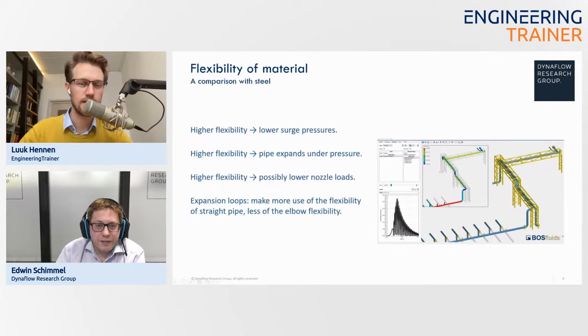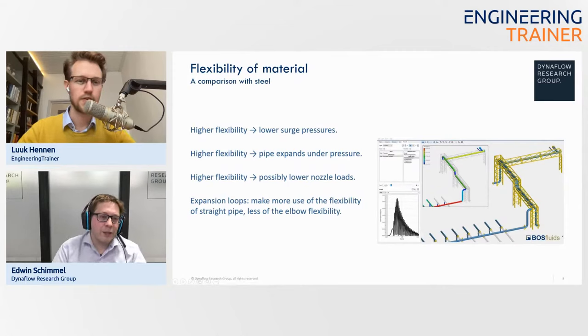Well, other differences. We have pipe expansion under pressure, which we don't have with steel. That is something different in your pipe design. For example, if you do a hydro test, that is the highest pressure that you will apply to your system in its lifetime, 1.5 times the design pressure. And the design pressure is, of course, already higher than the operating pressure. With the fiberglass pipe, you also see a lot of pipe expansion, whereas carbon steel hardly expands in the axial direction. With fiberglass, it does. If you hydro test a steel line, you don't see anything happening. It's just laying there. But with fiberglass, if you hydro test it, it will expand. So at the corner points, at the elbows, you really see it growing a bit.